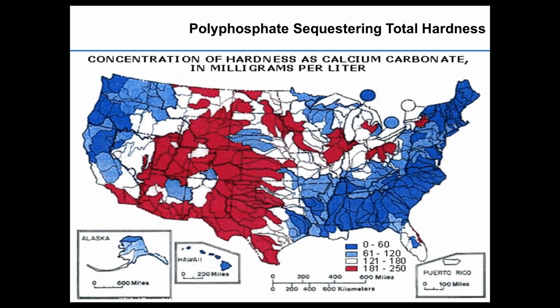One thing this map doesn't show is that groundwater can vary greatly from site to site throughout the U.S. Depending on what type of well you have and how deep the aquifer is will determine how much hardness you have to sequester in those wells. In the earlier case study for Carus 4100, that was a shallow well in Florida that did not have much calcium carbonate influence, so it had a very low hardness. In the Midwest and other parts of the U.S., you can dig a well and have 300, 400, or 500 hardness in the water, depending on that aquifer. So that'll determine how much scaling issues you could have in the distribution system.